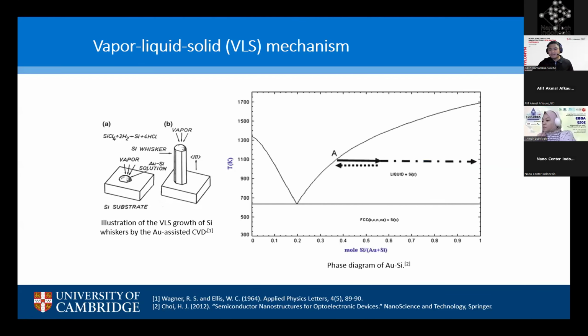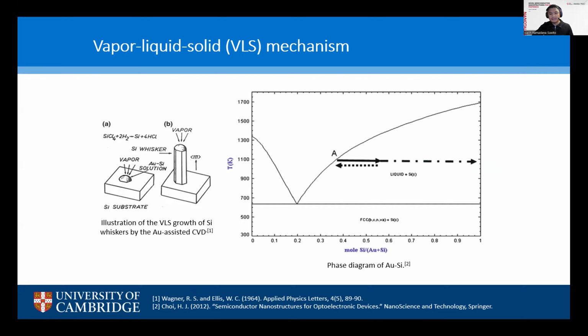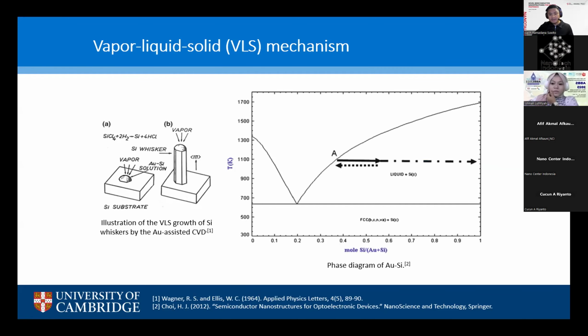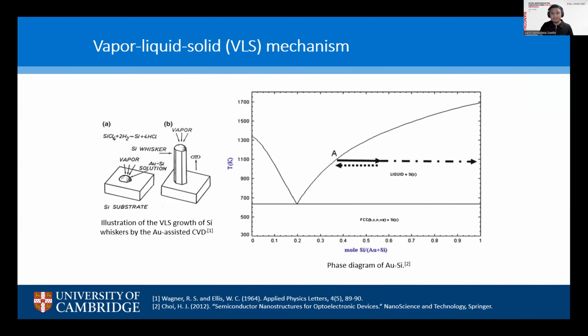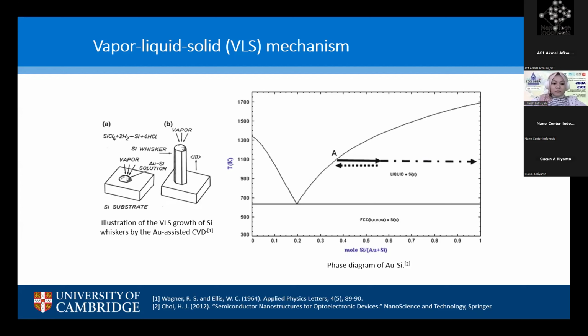And this kind of phenomenon can be understood by looking at this phase diagram. If you are coming from a materials engineering background, you would be more familiar with this one. This line here is called the liquidus line, which indicates the equilibrium composition of the liquid alloy at a given temperature. The y-axis is temperature, and let's say you are at point A here. Some thermodynamic fluctuation could dissolve more silicon into a saturated state, indicated by the solid arrow here. To compensate for the shift, solid precipitation of silicon happens, the dot-dash arrow here, and the liquid alloy shifts back to the equilibrium state. This process keeps going, and then you can have guided growth of semiconductors.